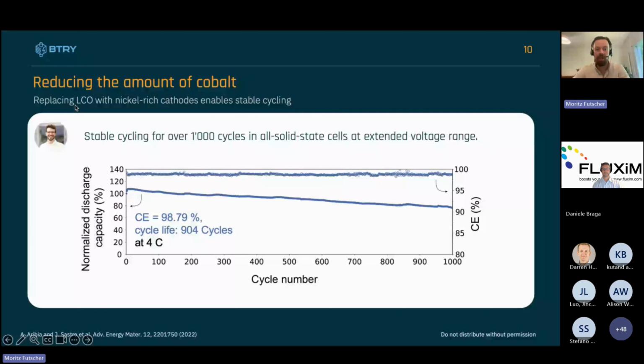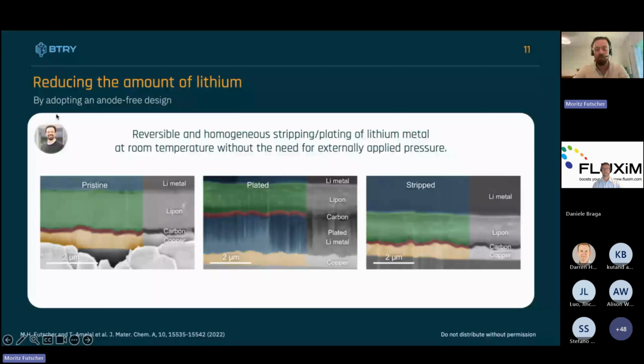On the other side, the anode side, and this is really where I focused during my research time, we were able to fabricate cells without an anode. So what does this mean? In a classical battery, as I've shown before, you usually have a cathode, the electrolyte or the separator, and then the anode. Now, the best performing anode in terms of energy per weight is lithium metal. Lithium metal is very difficult to handle and also usually has a tendency to grow dendrites. A dendrite is basically a spike which goes through your cell, and this can short circuit your cell. And then, of course, the cell is not working anymore.